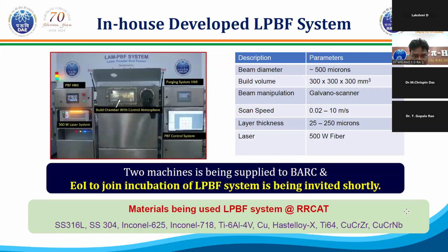This is a powder bed fusion machine that we developed, and we have tried many materials on it. We deposited SS316L, 304L, Inconel 625, Inconel 718, titanium 64. Copper was tried out, Hastelloy-X, and then copper chromium zirconium and copper niobium. This is basically a 500-watt fiber laser based system. Presently, the machine you are seeing has a beam diameter of about 500 micron, which simply means you cannot have features smaller than 500 micron, and the build volume is about 300 by 300 by 300 millimeter cube.